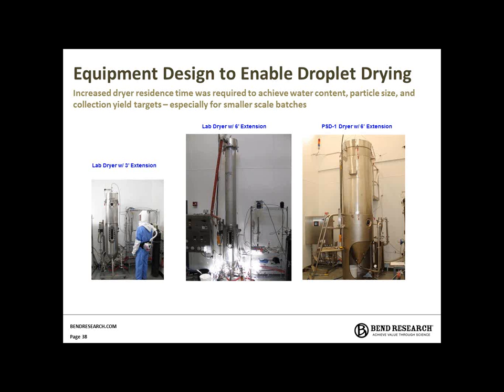With this particular formulation being a very viscous solution in low solids, we had to produce rather large droplets that dried a little bit maybe slower than we were used to, to end up with a dried product out of the spray dryer. So we adapted our equipment with these spray drying extensions to basically increase the residence time or drying time, which was required to achieve of course the right particle size, but also some of the other metrics, namely water content and yield, and especially at the smaller batch sizes we were working with.